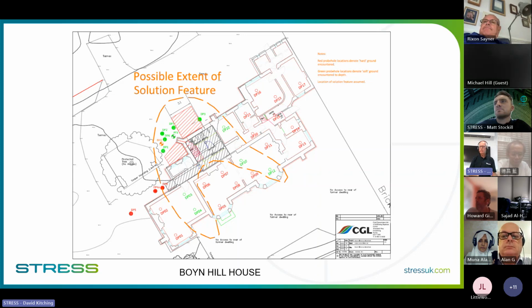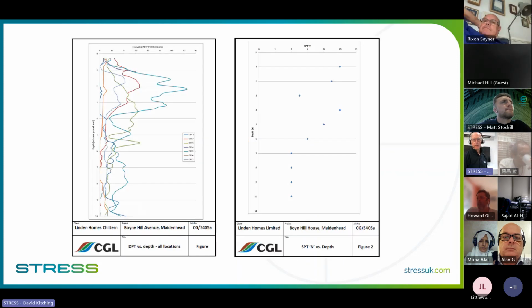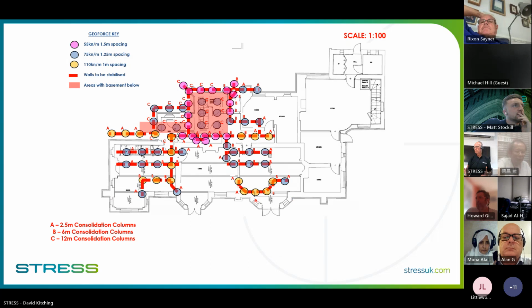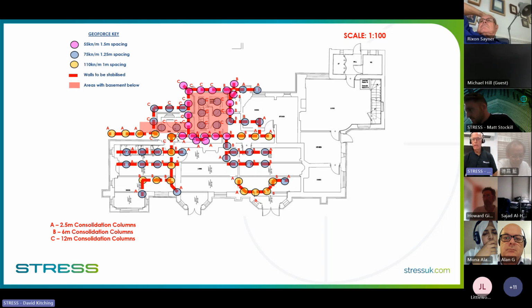This is what happened here. So we probed it. We got Card Geotechnics to come in, do probes inside and outside the building, to see if we could actually find the shape of this solution feature, and that's what we found. It looks a bit like a molar, and this is some of the sort of results we were getting. So we then designed a ReFORCE system, or in fact it was GeoForce in this particular case, because we're going down a bit deeper. We used almost scaffold tube size tubes, exactly the same technique, but we used a slightly bigger tube, and we then matched the loadings from the various walls and depths to create the support that this poor old priory needed.